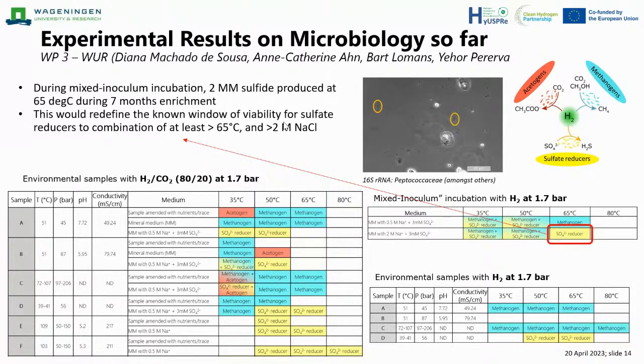Environmental samples are exposed to a hydrogen CO2 atmosphere at 1.7 bar. Also mixed environmental samples are exposed to pure hydrogen atmospheres of 1.7 bar. And also mixed inoculum incubations are used in the experiments with hydrogen exposure at 1.7 bar. And I think the most striking result so far is that Wageningen finds that at 65 degrees with 2 molar sodium and 3 millimolar SO4 sulfate, they find that sulfate reducers are active at 65 degrees, which basically extends or redefines the known window of viability for these sulfate reducers to this combination of at least 65 degrees and 2 molar sodium chloride.